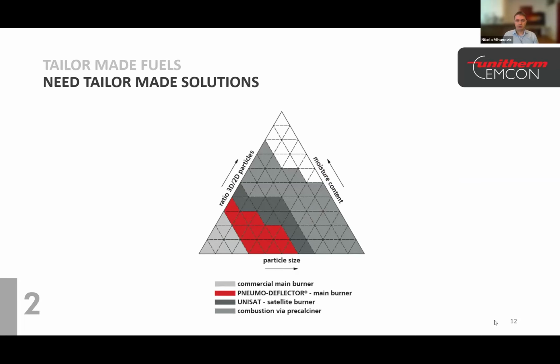Our research has shown that while various methods were attempted, including increasing injection speeds and using swirl, only deflecting particles above kiln axis effectively extends residence time and promote combustion. Over time, we successfully identified the optimal injection speeds and angles for each type and quantity of secondary fuel. With the use of pneumodeflector, we increase secondary fuel volume through the main burner by 10 to 15%, of course, by maintaining a consistent clinker quality. This was a theoretical part. Now we have some examples.